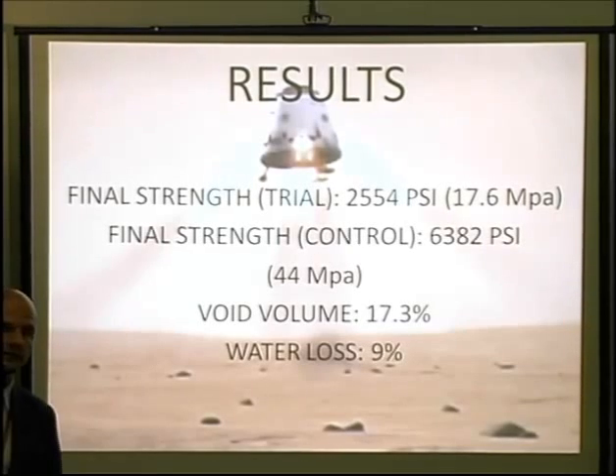I had 3 samples in the vacuum chamber that you can see, and 3 more samples that were cured outside of the chamber at normal atmospheric pressure. So those did not have the air voids. And the final strength of my trials in the chamber were 2,554 psi compressive strength, and the controls were 6,382 psi. I should explain the final strength I had before was after 7 days. This was after 2 days, only 2 days of curing. That's why the control strength is lower.